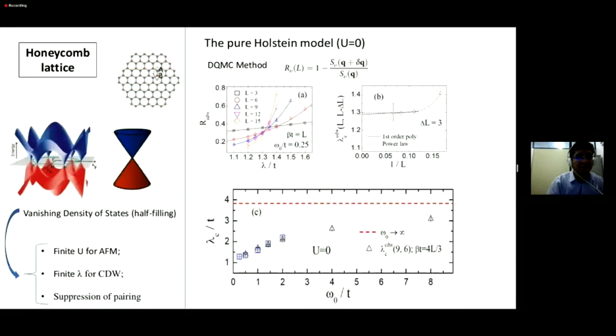So going further, for instance, analyzing the honeycomb lattice. The honeycomb is a little bit more complicated because we change the electronic dispersion. This vanishing density of states at half filling leads to a finite electron-electron interaction for antiferromagnetism and a finite electron-phonon coupling for CDW. This is already known, and it also leads to a suppression of pairing interactions, pairing correlations, actually. So the change of the geometry, analyzing this kind of Dirac electrons, changes everything.